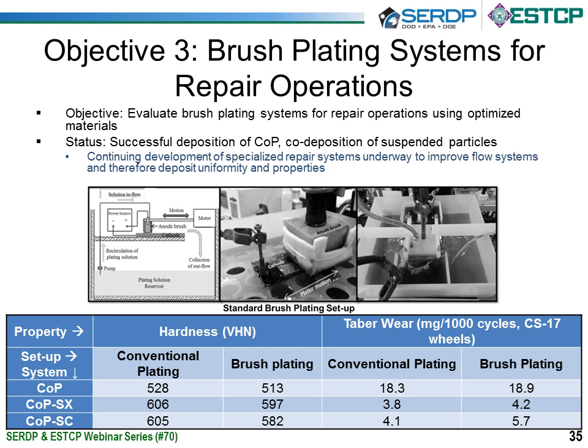So the last objective that we looked at was taking this new technology, the new process, and applying that to selective area repairs. First, we looked at brush plating. So basically, rather than dipping your part in your tank, now we're using brush plating to flow solution through a brush plating head onto a sample and then coating it. So we produced a number of samples and we looked at the hardness as well as the Taber wear. And we saw similar performance of the tank plated material as we did with the brush plating. So we saw a significant reduction in the Taber wear as well as an increase in hardness with the incorporation of particles.